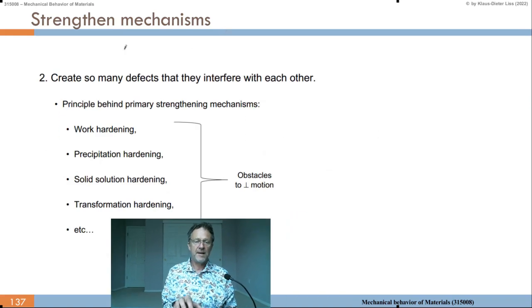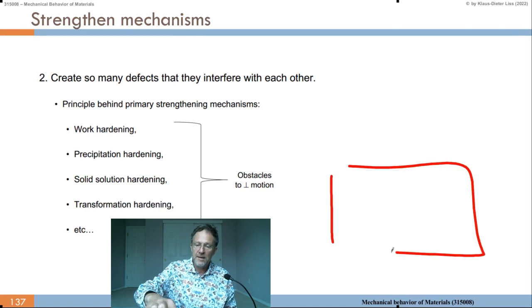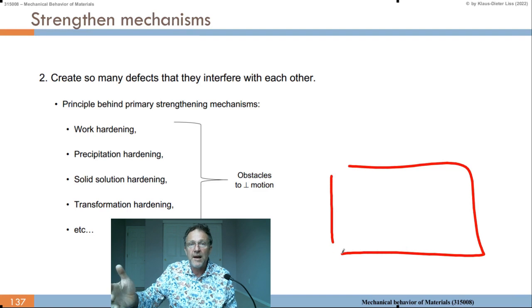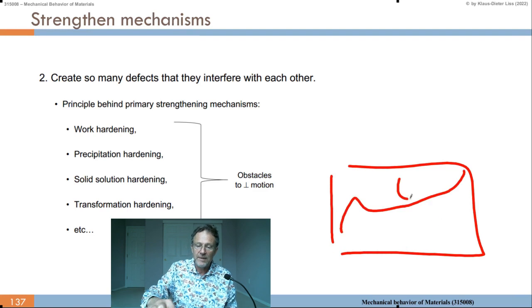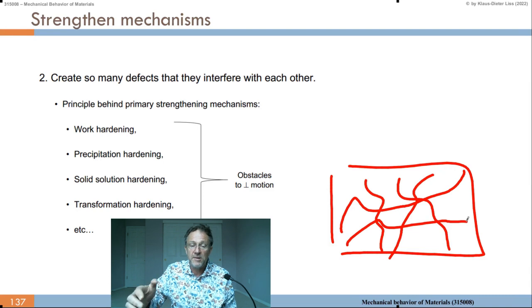So the strengthening mechanism is we create so many defects in the crystal that they interfere with each other. For example, dislocations. The principles behind strengthening mechanisms are work hardening, precipitation hardening, solid solution hardening, and transformation hardening. In work hardening, if we have a crystal or crystallite within the microstructure, then we get dislocations here, there, and eventually they interact with each other.